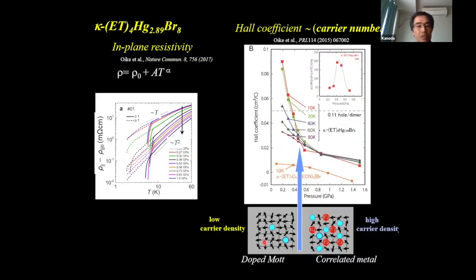Okay, time is running out, so I should go in a hurry. Okay, this is the pressure dependence of the Hall coefficient. Please take a look at the low temperature behavior, 10 kelvins. At low pressures, the Hall coefficient is large. This means that the density of the holes is very, very small. However, at high pressure regions, the carrier density is large. So I think that around 0.5 GPa, some change occurs from a low carrier density liquid to a high carrier density liquid crossover.